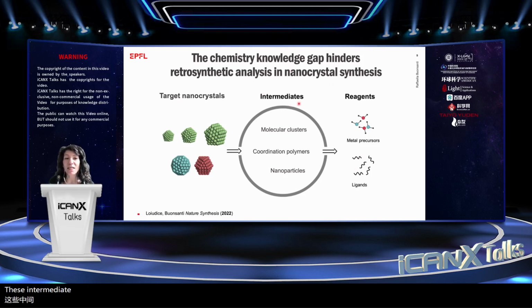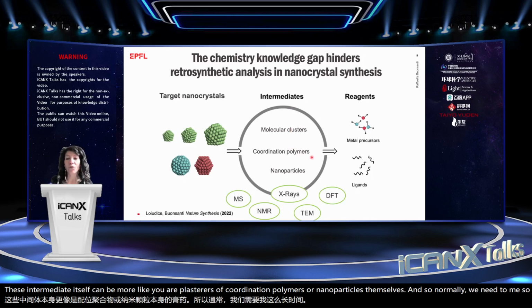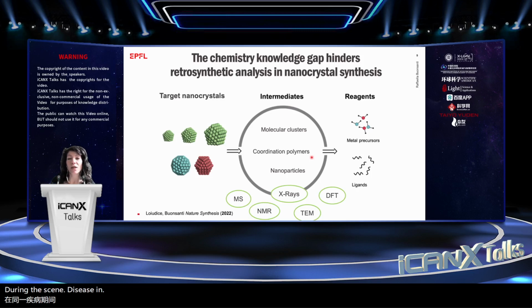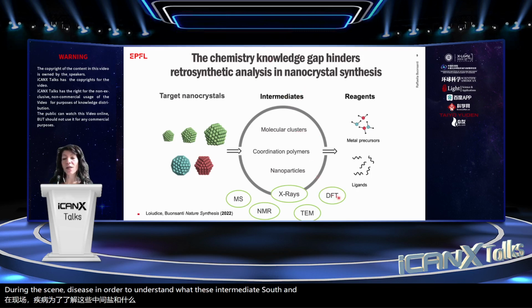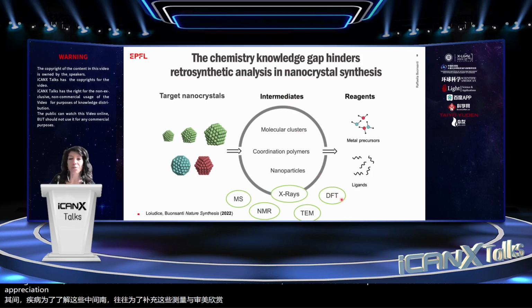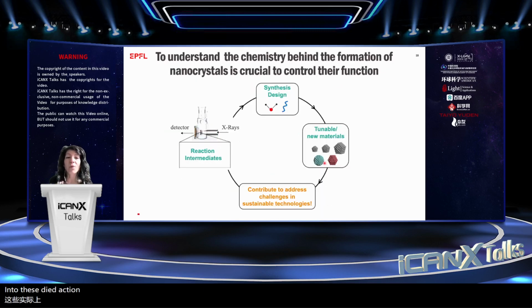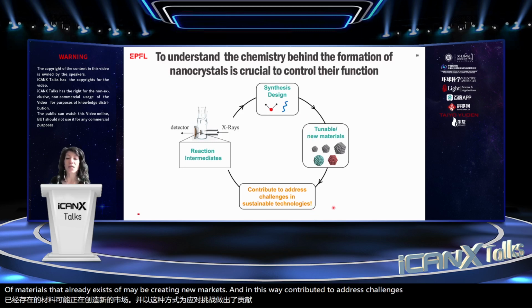These intermediates can be molecular clusters or coordination polymers or nanoparticles themselves. And so normally we need a miscellany of characterization techniques during the synthesis in order to understand what these intermediates are, and often also to complement this measurement with DFT calculation. However, in my group, we spend quite substantial effort in this direction, and we demonstrate that if we are able to understand what the reaction conditions are and what the chemistry behind the formation of nanocrystals is, we can design more advanced synthesis schemes, and then eventually increase the tunability of materials that already exist, maybe create new materials, and in this way contribute to address challenges in sustainable technologies.